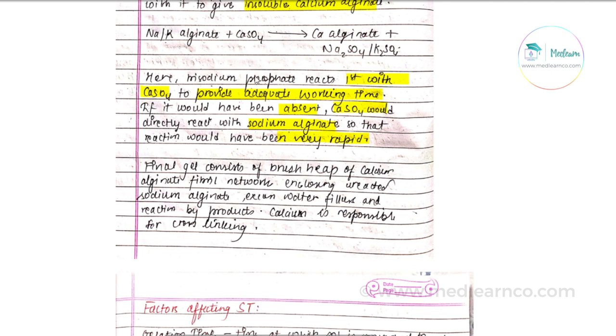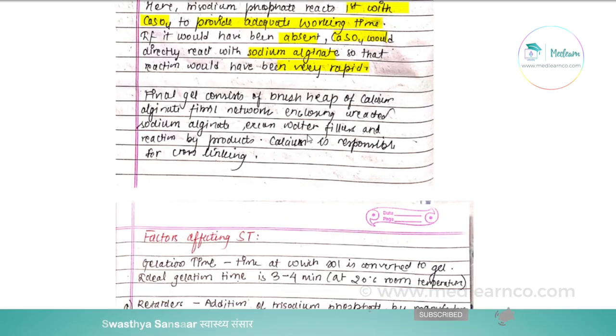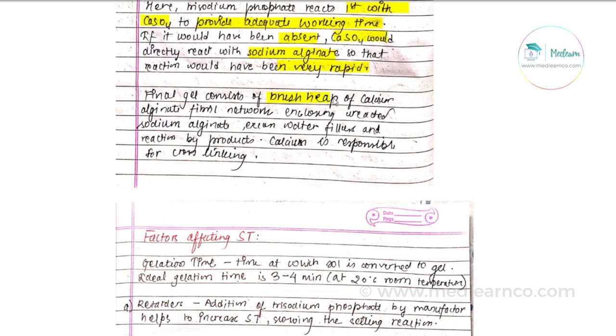The retarder provides adequate working time. The final gel consists of a brush-heap of calcium alginate fibril networks enclosing unreacted sodium alginate, excess water, fillers, and reaction byproducts. Calcium is responsible for cross-linking — the fibrils are cross-linked by calcium.